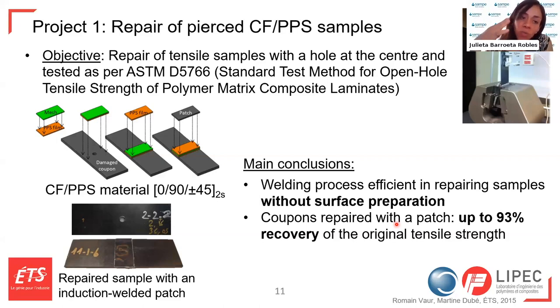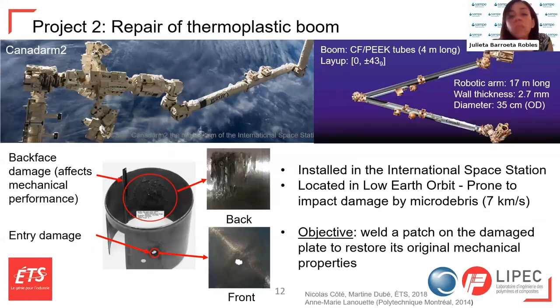This research work then led to a second project at the École de technologie supérieure, which involved the repair of a thermoplastic carbon fiber PEEK boom, which is representative of the Canadarm2. The Canadarm2 is installed in the International Space Station and it's located in low Earth orbit, which makes it prone to impact damage by micro debris. So we can see here what type of damage this micro debris can cause to the structure. As we can see, the entry damage and the back face damage are quite different. And there's extensive damage in the back face, actually causing delaminations.